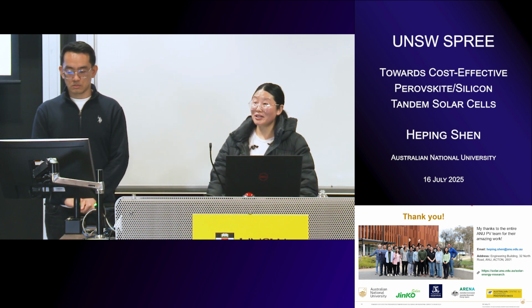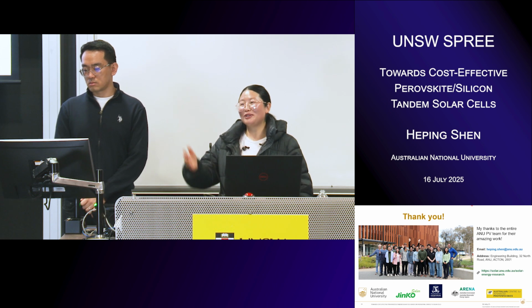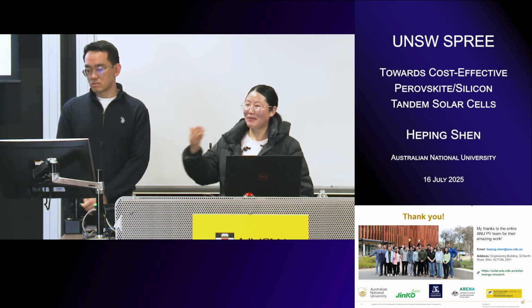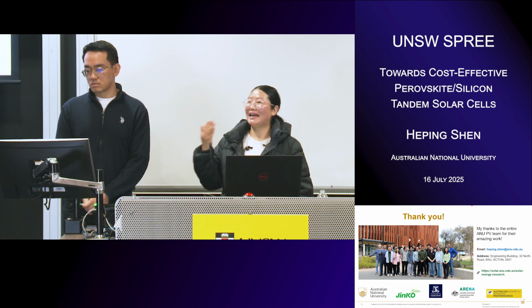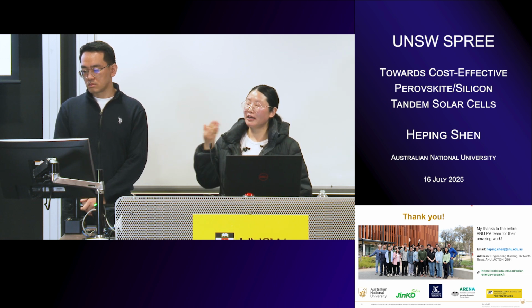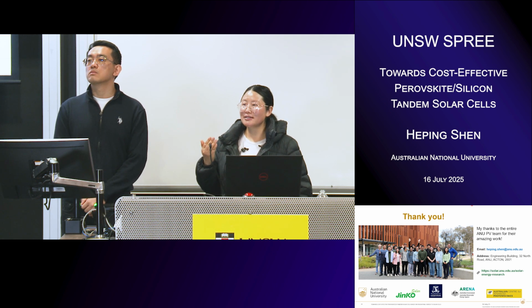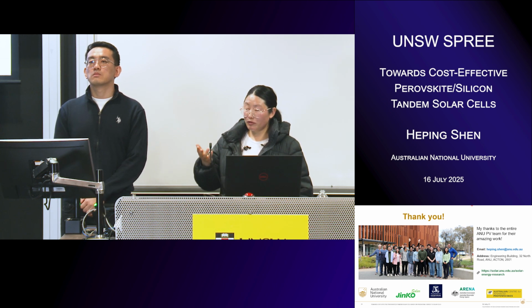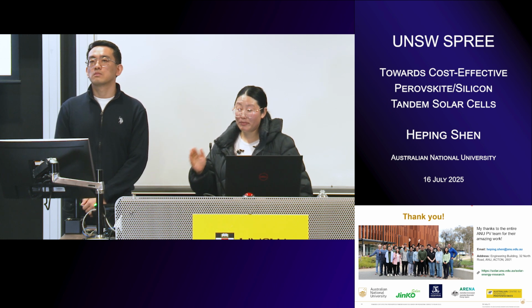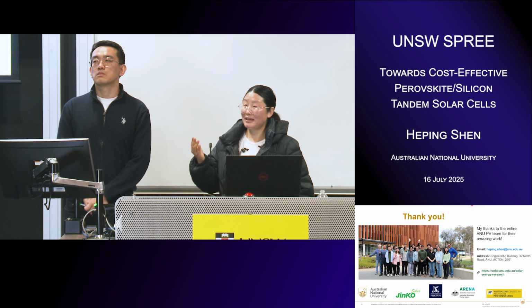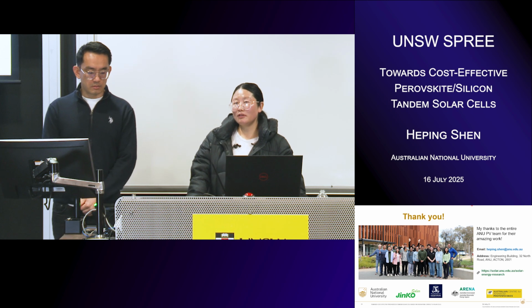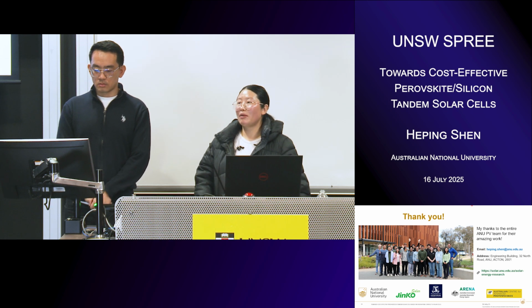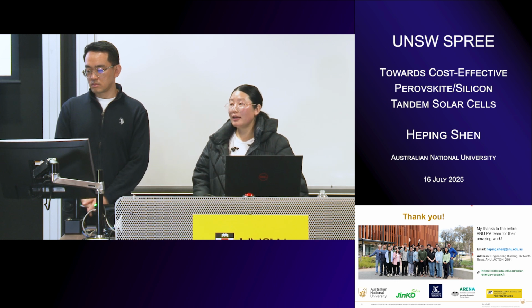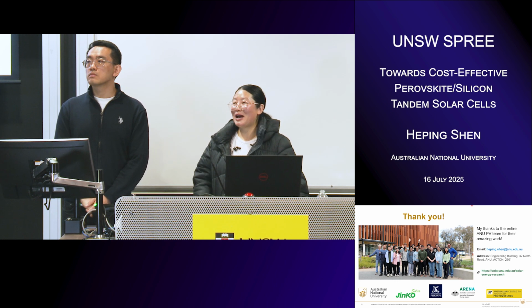Oh, okay. Yeah, that's a really great question. You have provided a lot of information that adds to my statement that for PIN and NIP, they both have their own advantages, but also their own challenges. For the PIN, for your particular question, in terms of replacing carbon-60, which is a big problem not only for the absorption loss, but also for the mechanical stability, one of the structures I believe might be very promising and has been proven to work efficiently is to completely remove the carbon-60 and use tin oxide directly on top of the perovskite.